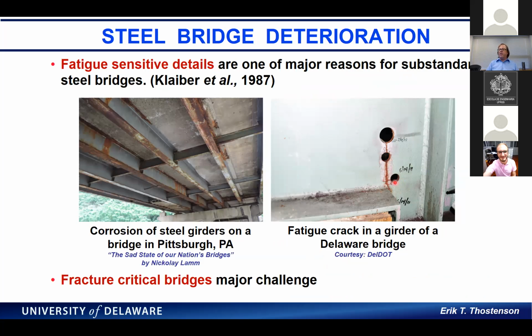And what you see here, these dark areas, is where they drilled what we call a crack stop hole. That blunts the crack's tip, and also drills away some of the strain-hardened steel out of the crack tip. So these fracture critical bridges are a major challenge, and there's a lot of interest in that. This is intended to be a repair technique, but it's not always very effective. Here you can see they drilled a hole, and then that crack reinitiated. So then, a couple of years later, they drilled a bigger hole.